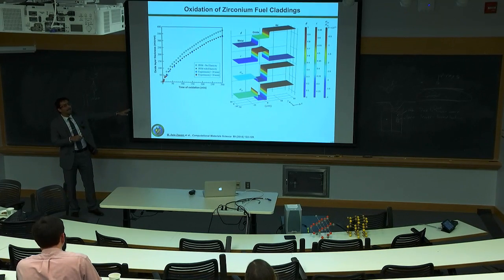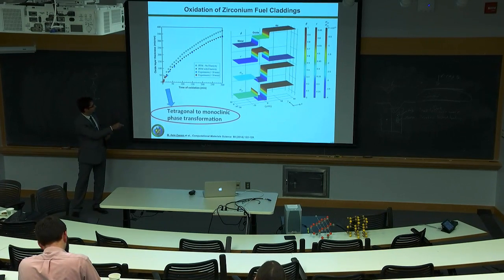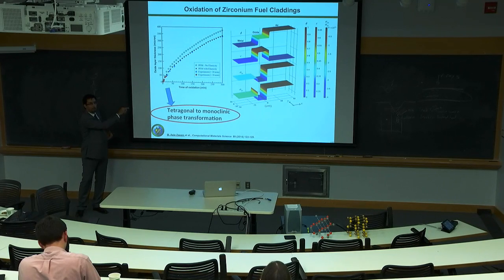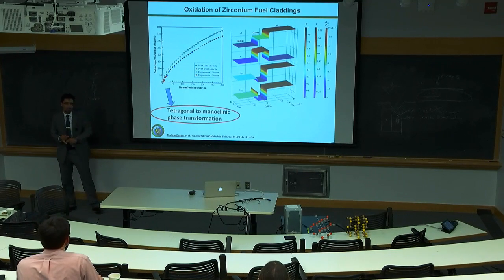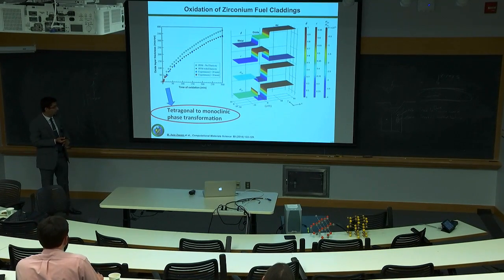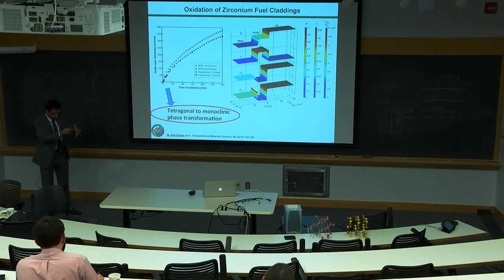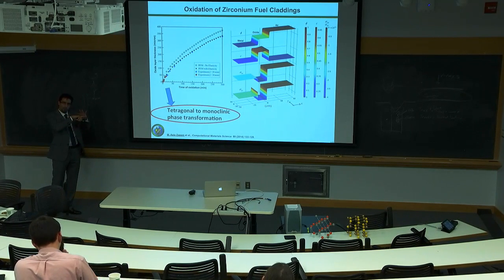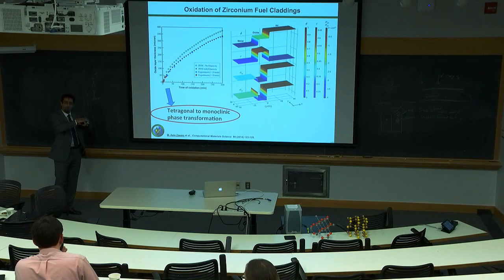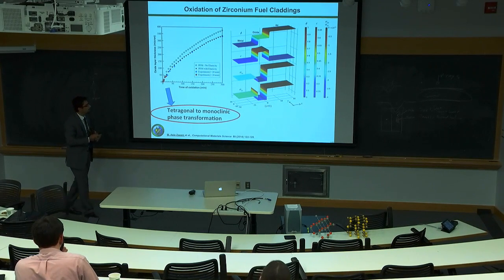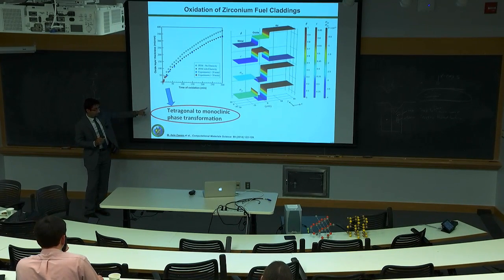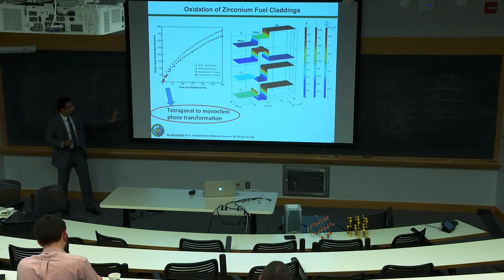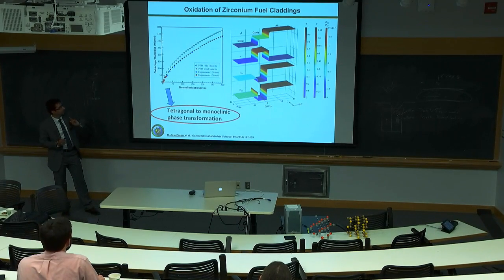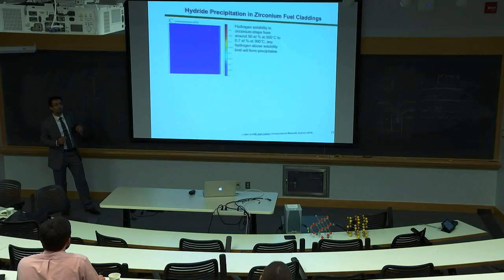What this model cannot predict is the phase transformation happening here. This phase transformation is actually the key to starting to completely destroy the cladding. Because of the phase transformation, we are going to have volume expansion and lots of cracks. The next one, just one page on hydride precipitates. So hydrogen will react. What happens when hydrogen reacts?